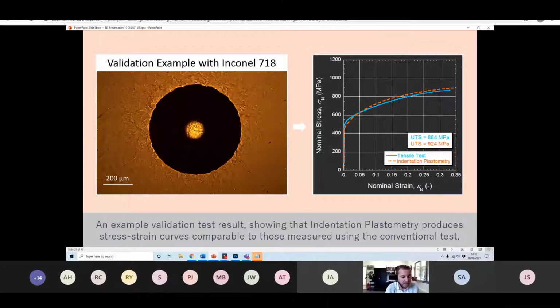Maybe more importantly, on the right-hand side, what you can see is a comparison between the stress strain curve measured using the conventional tensile test machine and the stress strain curve that was inferred using the indentation-based method. And naturally, the agreement is very good. I'm sure you wouldn't expect me to show anything else, but I think it's important to point out that the key features are being captured here. That is yield stress, hardening behavior, and of course the UTS. And in fact, in more recent versions of our software package, we also pull out post-necking behavior as well.